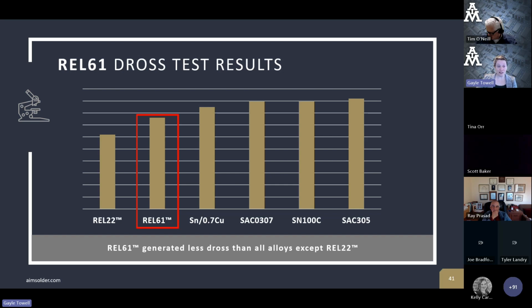We have a lot of people ask about dross. If you run a wave solder pot, you're going to have dross, and you don't want dross. Again, we talked earlier, that's why some of these alloys will contain phosphorus to mitigate that. REL61 doesn't have any phosphorus added in our bar, because it doesn't need it. It naturally drosses less. We did a dross study where we melted each of these alloys under identical conditions, stirred them up under identical conditions, and saw how much dross formed over a period of time. The winner was REL22, our super high reliability alloy. Coming in second place is REL61, outperforming all of these other alloys, SAC305, SN100C, 0307, and so on. So if dross is a concern, which it often is, especially if you're considering a new alloy in your wave pot, rest assured, REL61 is going to improve results there as well.